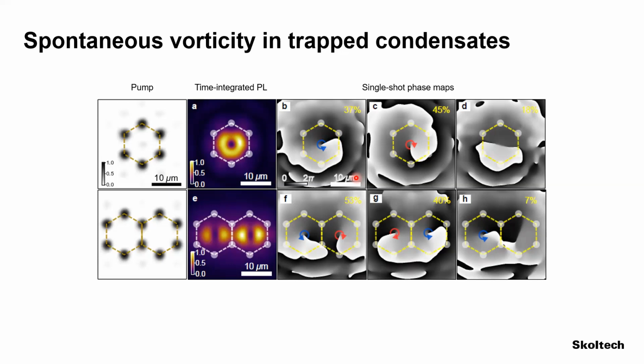anti-clockwise rotating vortices. They don't follow the statistics of the one. They like to go in opposite flows. So practically where they meet, they have opposite flows so that they reduce the friction. So two quantum vortices which are coupled, they like to go in an anti-ferro configuration, spin up, spin down.